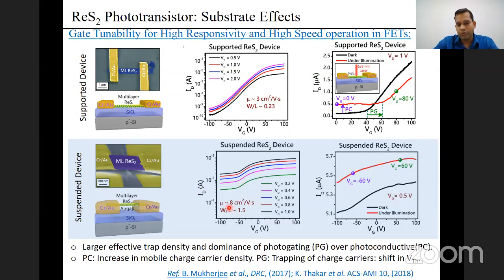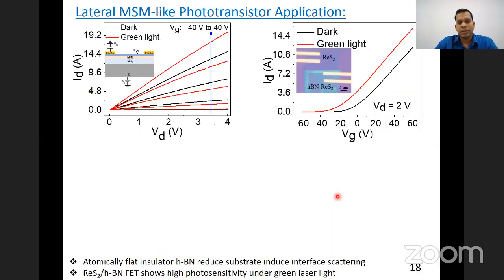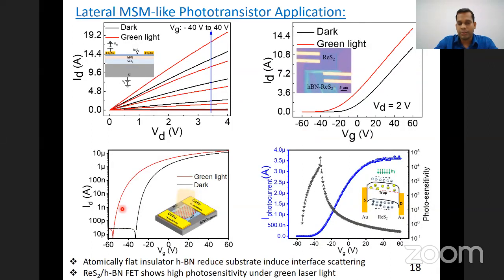But there is another problem, that we do not have much gate control on the drain current. Of course, there is good photoconduction over the photogating effect, but we have less tunability. So that we can easily solve by using this type of device, where we use hexagonal boron nitride as an interfacial layer between rhenium disulfide and silicon dioxide. That actually suppresses the interface trap states of SiO2, and it is also a quite good dielectric material. So it will increase the gate control over the drain current. And then we see quite a large enhancement in the current, and the threshold voltage also shifts to the left, because it is an n-type conductor, and the photogenerated holes get accumulated. So there will be a threshold voltage shift. And the photosensitivity value which we see is quite huge in this threshold voltage region, with good photocurrent at 532 nm laser illumination. So basically this will be a good candidate for phototransistor application.